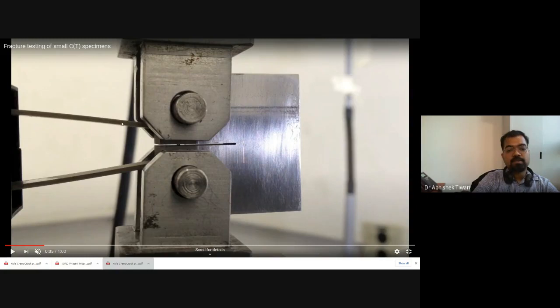And there is a correlation, because this gauge is attached at the surface. However, the crack is far ahead of that place. So there is an assumption, which is not very wrong, that these areas will be deforming elastically and the crack tip will obviously be deforming plastically if we're talking about elastic plastic material. So there has to be a correlation which relates how much this tip will open up, and that can be calculated from this. Why do we do this? Because when these two pins go up, there's a rotation involved, and therefore the displacement of these pins, which the machine usually measures, will not be the correct displacement happening at the crack tip. So you need these kinds of devices to find out what happens at the crack tip.